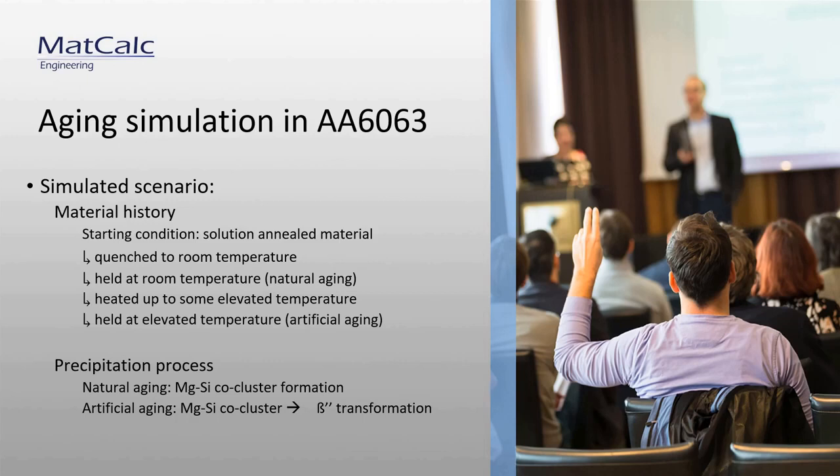We will simulate first an isothermal holding at the room temperature, starting from the solution annealed material, which will be quenched to the room temperature. Next it will be held at the room temperature, so that some natural aging processes will occur in the system, during which the co-clusters of magnesium and silicon form.